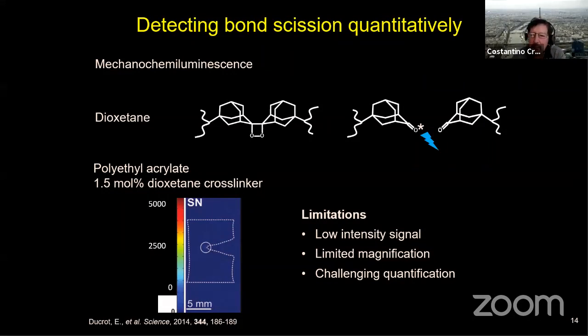In the previous example, we were trying to measure stress directly by using a molecule. Now, detecting bond scission, we had done that with the luminescence experiment. This was the paper published in Science with the dioxetane. So in a way, it's a fascinating molecule. It gives you a signal when it breaks. So you have time-resolved data.